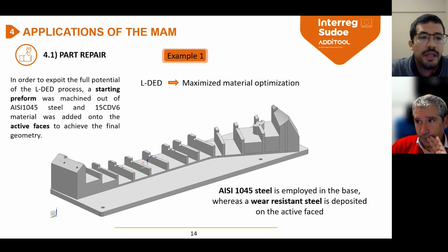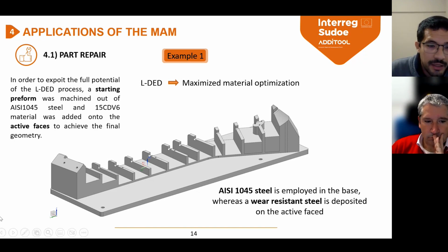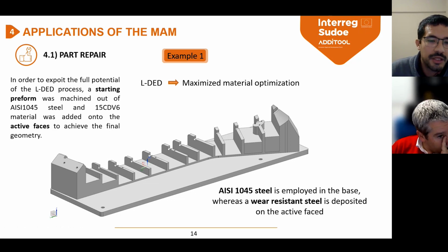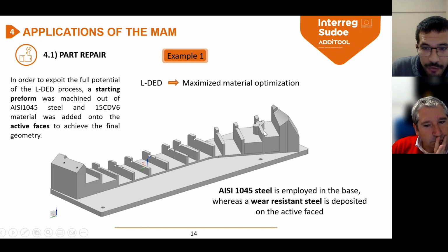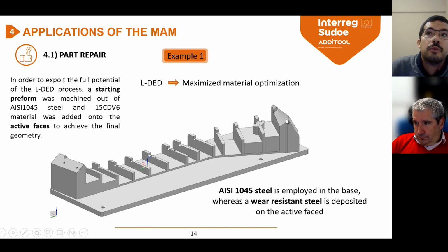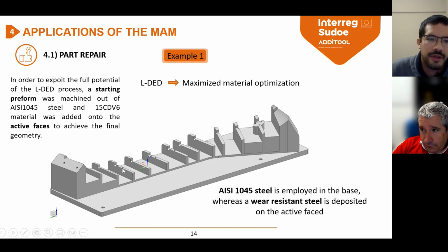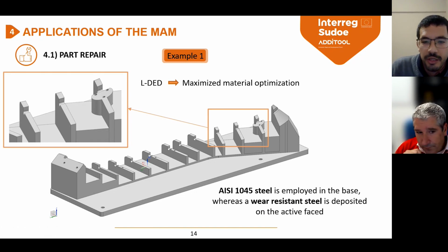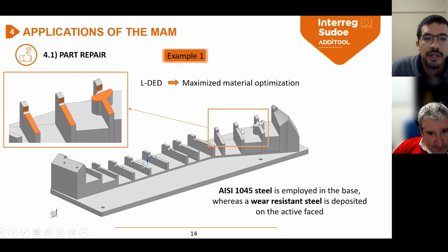Okay, so in order to give one example for the part repair, this is a case study that we have manufactured inside the ADDITOOL project. This is a clamping device in which we have to position a stamped part, and we will use it to check whether the stamping process has been properly manufactured. Traditionally, this part was built in 15CDV6, which is aeronautical steel, quite expensive and not so easy to manufacture and work with. Instead of doing it that way, we have tried a new strategy, which is building the base in C1045, which is a common steel, rather cheap and easy to manufacture. Then we eliminate 1 millimeter of material in the active surfaces and we fill it with the good 15CDV6 material.